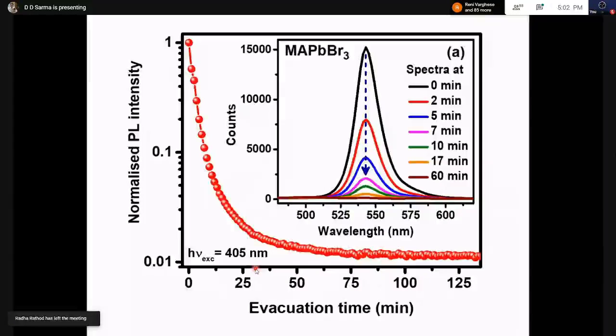Now, when you lower the temperature, you don't want the sample to remain in air because then everything will condense on it. So what you do is put a vacuum shroud around the sample and evacuate the surroundings of the sample so that it remains clean. We didn't start to cool down the sample. We did this setup and started evacuating.